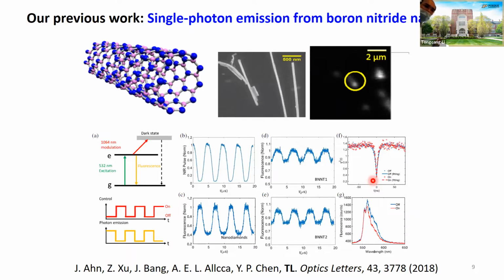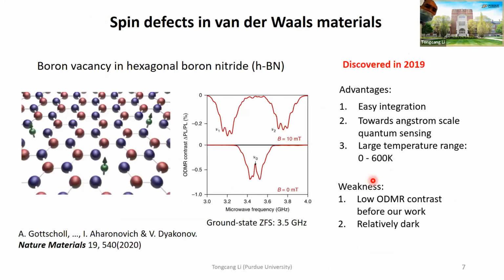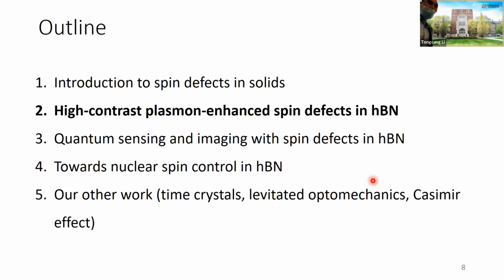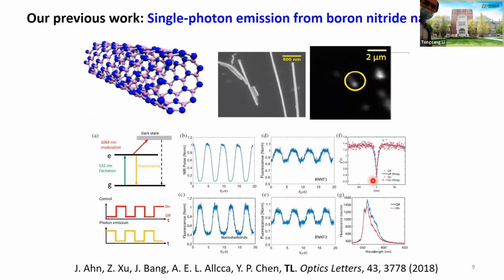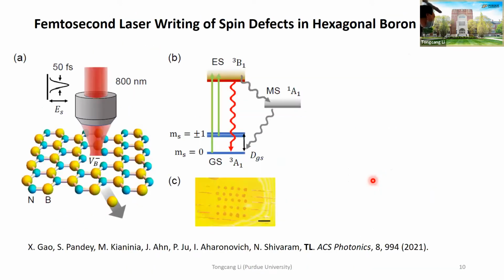So now, if we want to work on this, the first thing is we need to create boron vacancy defects. In the original work, when they published this paper, they used a neutron source to irradiate the boron. The neutron can be captured by boron and cause a nuclear reaction. So it is quite difficult. We don't have a neutron source. So first we tried femtosecond laser writing of the spin defect.